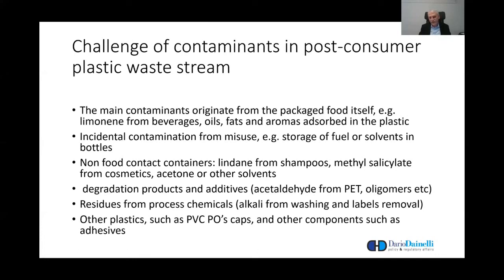Degradation products typical from PET is acetaldehyde, but also you might have oligomers in all kinds of plastics, particularly polyolefins. There might be residues from chemicals used in the process, such as alkali from washing and removal of labels, and other plastics which might taint the stream that is to be recycled. For example, in the PET recycling, presence of PVC, polyolefin caps, and other components such as adhesive, they are in fact detrimental to the quality of the stream.